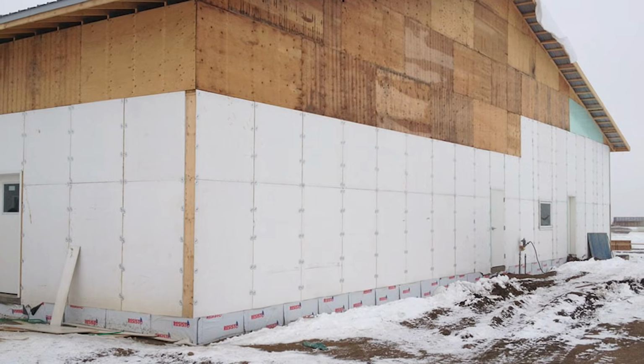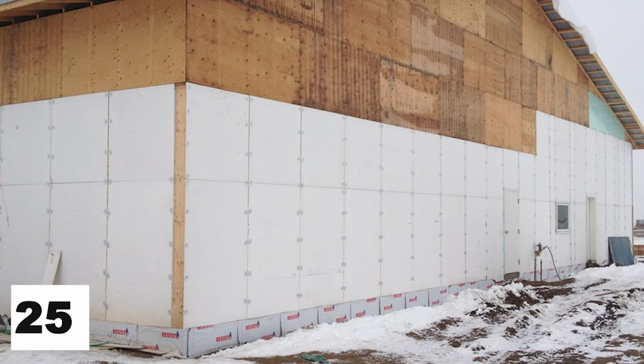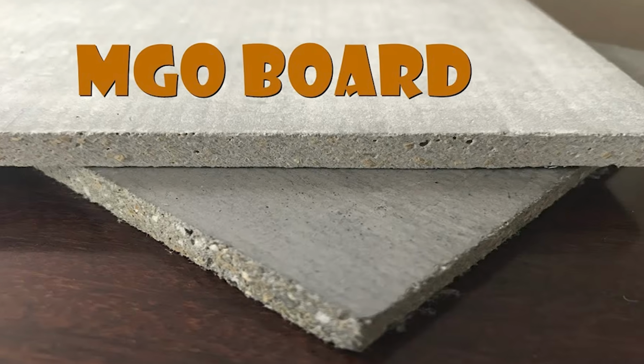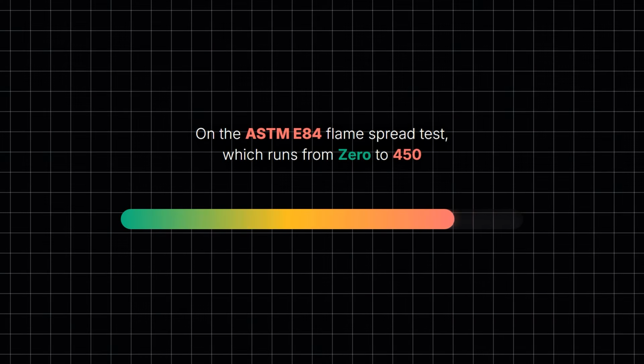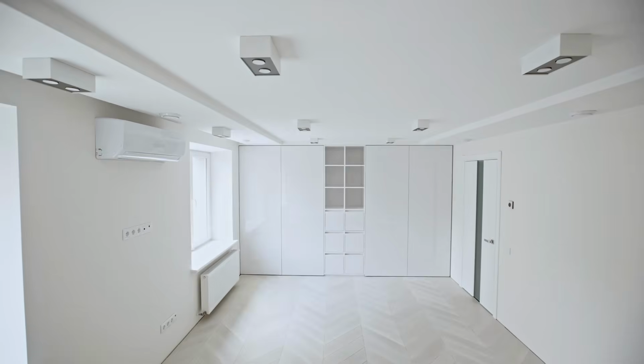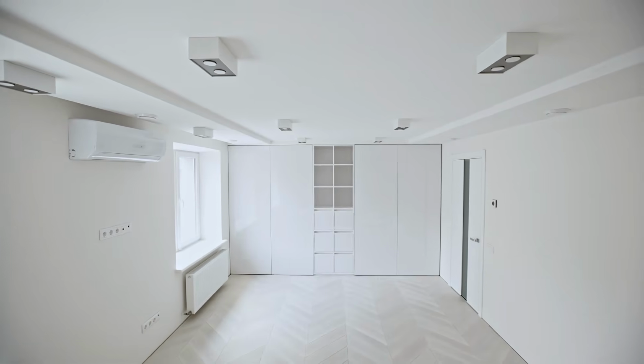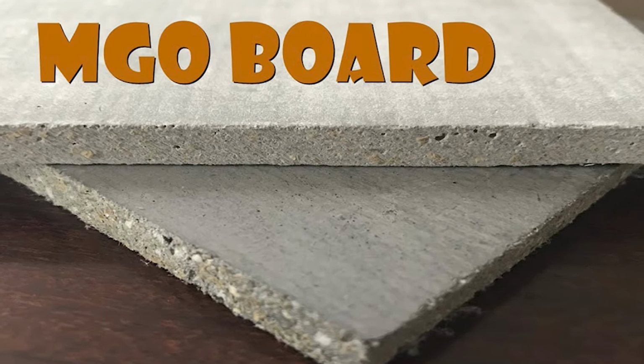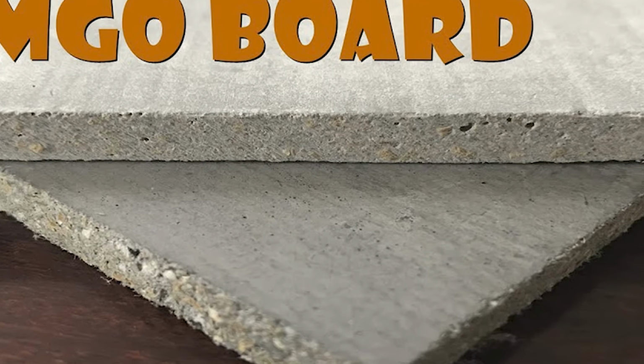In moisture cycling tests, 25 cycles of complete immersion followed by complete drying, OSB lost 40% of structural strength. Gypsum drywall lost 52%. MgO board lost none. On the ASTM E84 flame spread test, which runs from 0 to 450, with Class A materials scoring between 0 and 25, gypsum drywall scores 0 to 15, and OSB scores 76 to 200. MgO board scores 0 for both flame spread and smoke development.